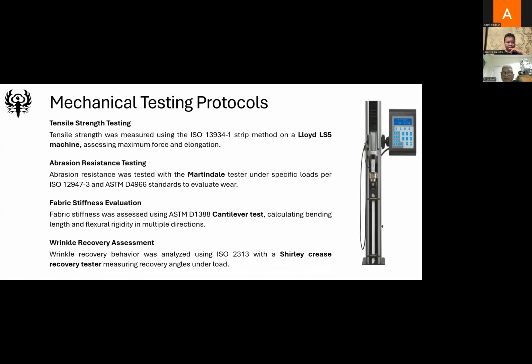Okay, so to prove the objective of the research, they conducted some mechanical testing. The first one is tensile strength, using a Lloyd LS5 machine. They also tested abrasion using Martindale, the fabric stiffness was measured using a cantilever test, and the recovery was assessed by Shirley.